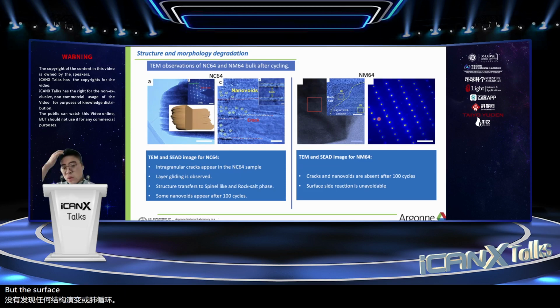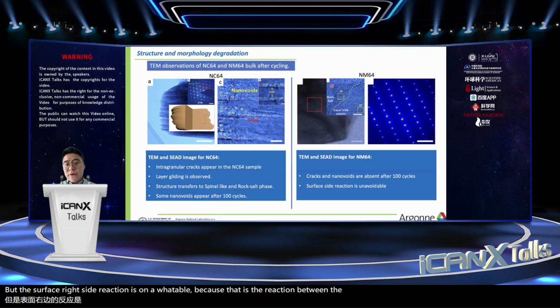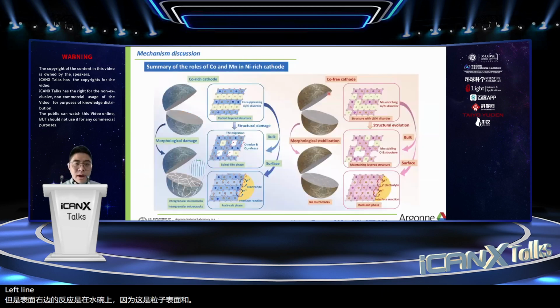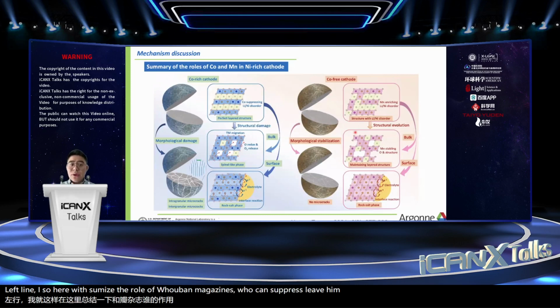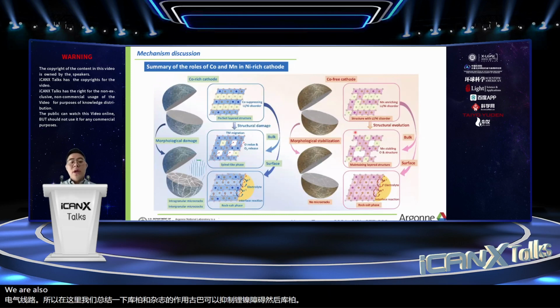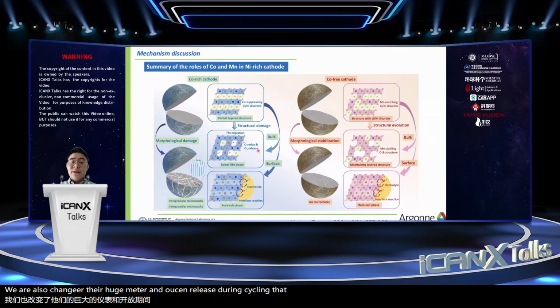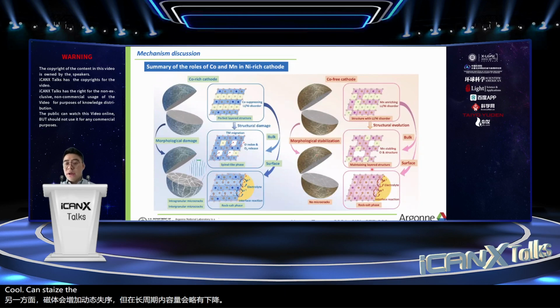but the surface side reaction is unavoidable because that is the reaction between the particle surface and the electrolyte. So here we summarize the role of cobalt and manganese. Cobalt can suppress lithium-nickel disorder, but cobalt will also trigger the huge lattice parameter change and the oxygen release during cycling. That is the disadvantage of cobalt. On the other side, manganese can increase the lithium-nickel disorder, and then the capacity may drop a little bit. However, during the long cycle, manganese can stabilize the structure to get better cycle performance.